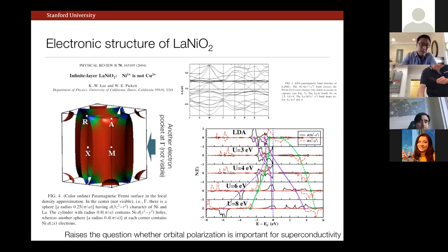So that in some sense gives you a natural explanation of why we don't have a good insulator. Various people, Fucheng Zhang, for example, have used the term of a self-doped Mott insulator, that because of these peculiarities of the band structure, there is internal kind of charge transfer and partial doping, or having partially occupied states.